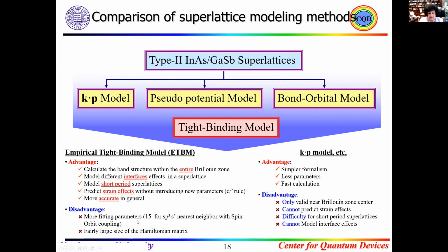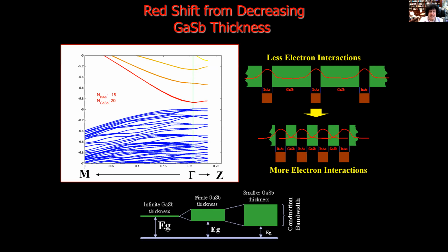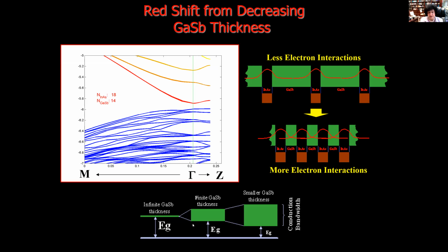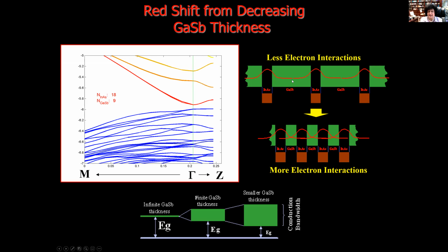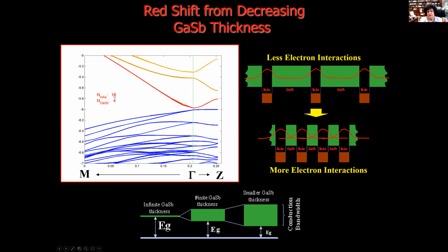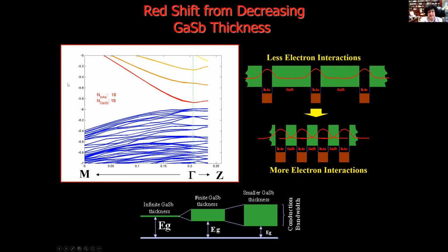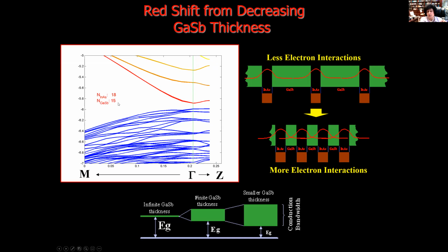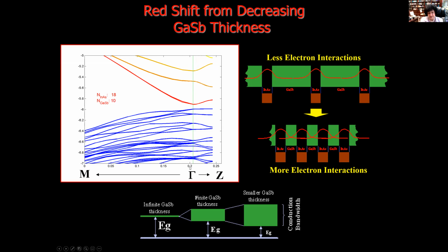But the disadvantage is, of course, we have a lot of different parameters, especially we can have 15 if we come with the sp3 and at the same time the spin orbit coupling, and it needs a large size of Hamiltonian, but that we can manage. And exactly as you can see here, if I take the indium arsenide and gallium antimonide, exactly as I mentioned, if I keep one of the materials fixed and change the other one by 1 or 2, here we have the center of the Brillouin zone.